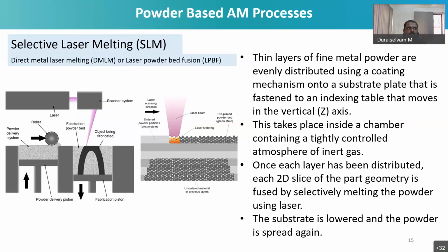Nowadays, they have systems that can accommodate any powder when it meets the specification constraints of the OEM, and you have the liberty. Earlier, it was not the case. You needed to purchase the powder from the OEM, and that ultimately affected the end product cost. But nowadays, you can procure the powder from anywhere. The only thing is you need to look at the powder particle size, powder shape, and if you sieve that powder using the siever provided by the manufacturer, then confidently you can use the system for producing any kind of